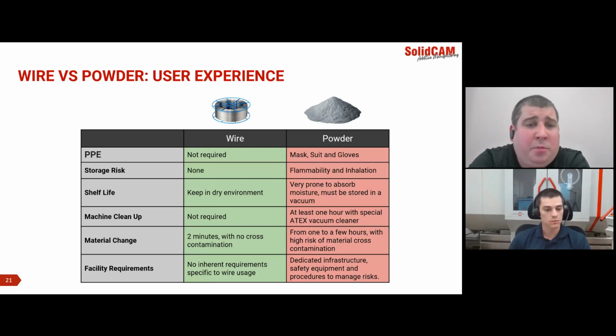Mostly, in terms of protecting the machine tool, we don't have to worry about any type of hazards with reactive materials like aluminum and titanium being in a powder form. With wire, it's inert, so we don't have to worry about any PPE to handle the wire. It's not a concern compared to powder. As well as storage, we don't have to worry about storing our wire in a special enclosure, simply keeping it in a low humidity environment to prevent oxidation with most materials. You also don't have the coolant contamination like you would have with a powder system inside of a machine tool.